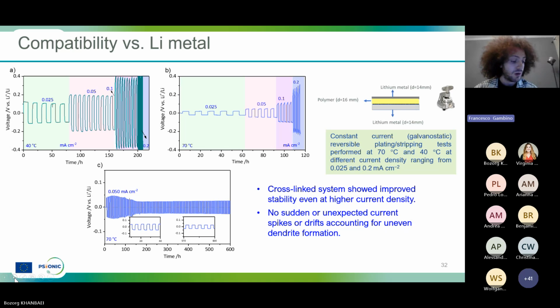Also, we performed a prolonged plating and stripping experiment to ensure the stability and the safety of this membrane. And we can see that after 600 hours of cycling, there are no spikes or unexpected shift in the current that can account for uneven lithium deposition or dendrite formation. Next slide, please.